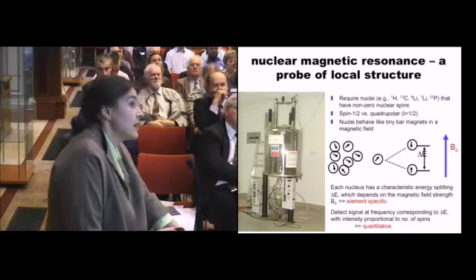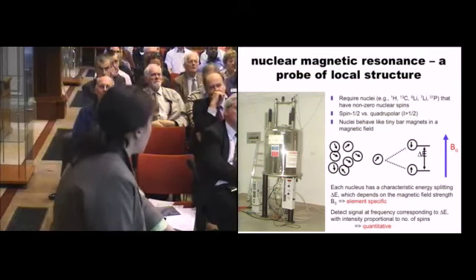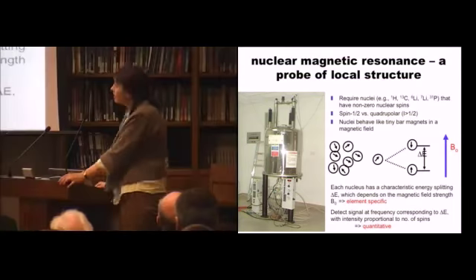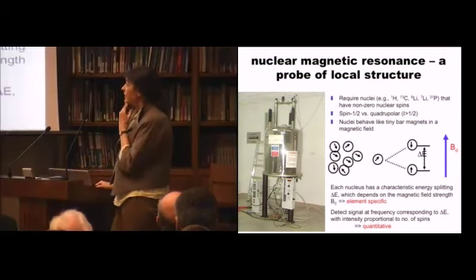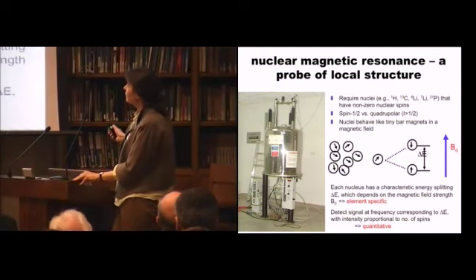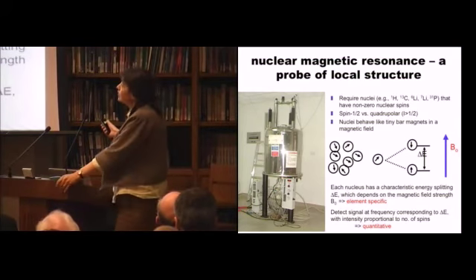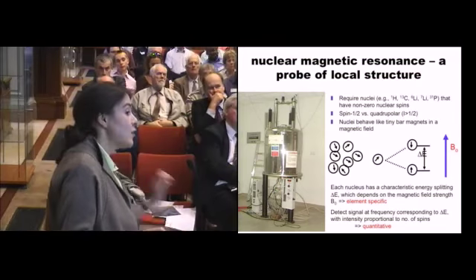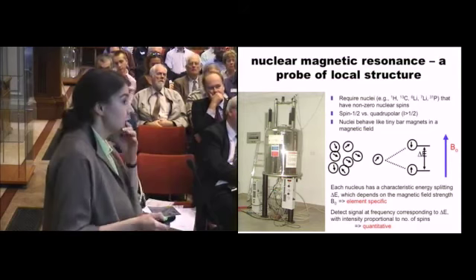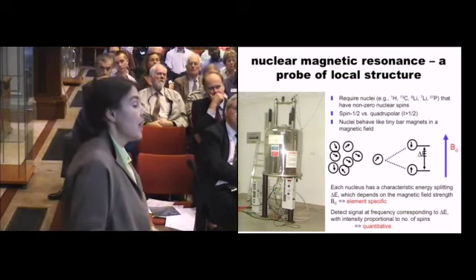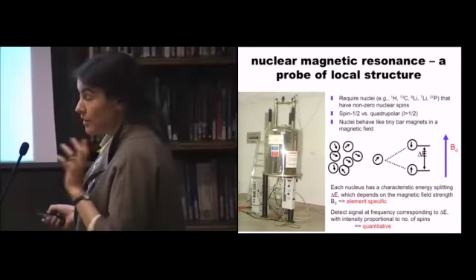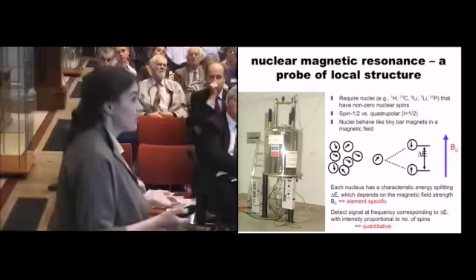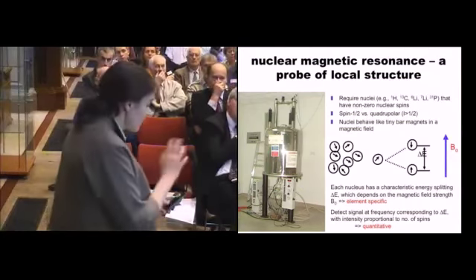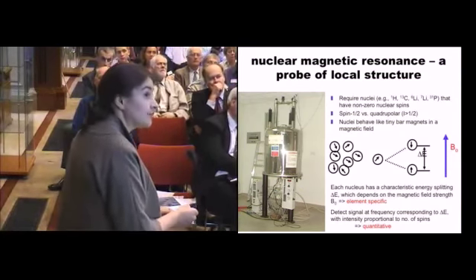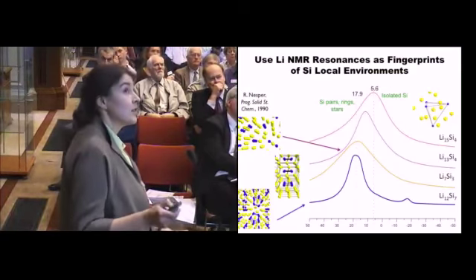So what we do is use a technique called nuclear magnetic resonance. This is analogous to MRI, magnetic resonance imaging, except that we do spectroscopy rather than getting an image. The advantage of NMR in this field is that lithium has two NMR-active nuclei with nuclear spins, lithium-6 and lithium-7, and you can think about those as little spies that interrogate the local structure. So it's an element-specific method: I zoom into the lithium. It's quantitative, so I can count how many different environments I have, and it tells you something about the local environment around those nuclei. So I can use lithium NMR as a fingerprint of different local environments.